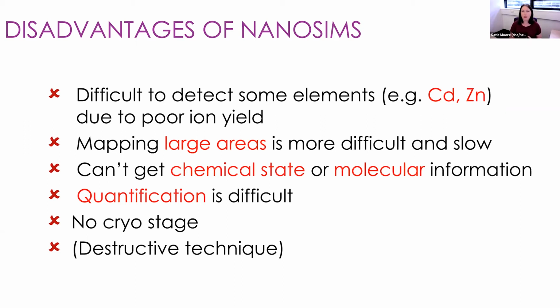If you want any chemical state information, you're probably better off going to look at X-ray photoelectron spectroscopy, for example. And you may have come across SIMS before and know that it can provide molecular information. That is a slightly different kind of SIMS instrument you need for that. That'd be a time of flight SIMS. The NanoSIMS tends to give just elemental or isotopic information.